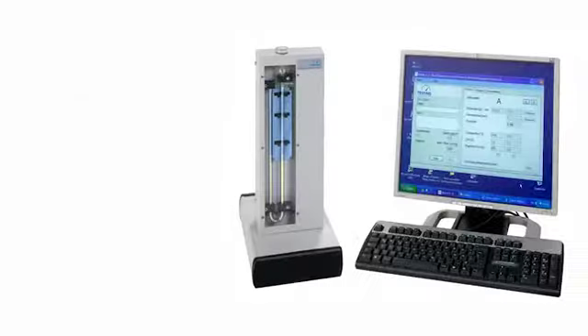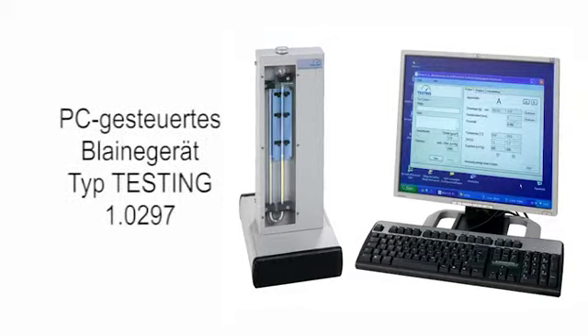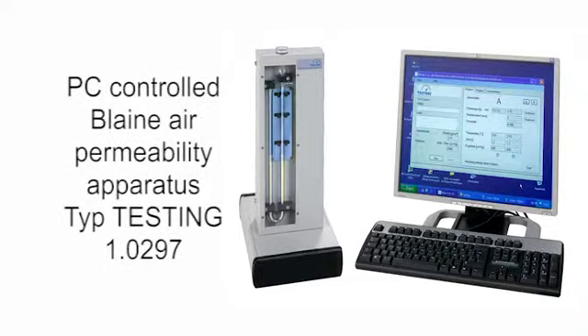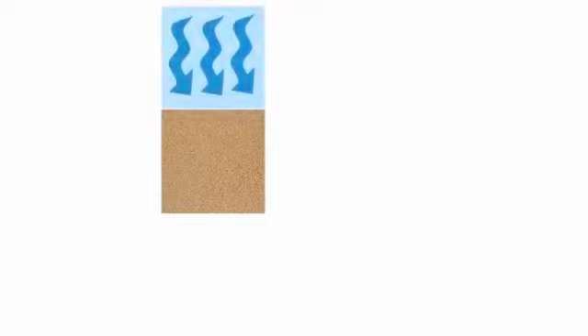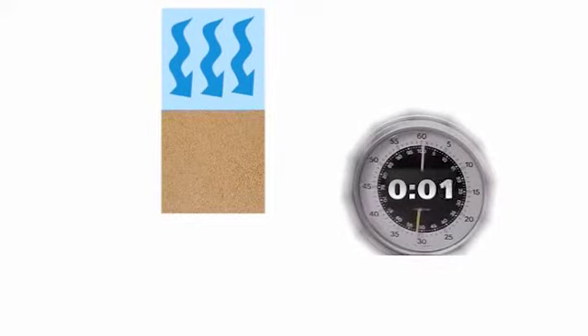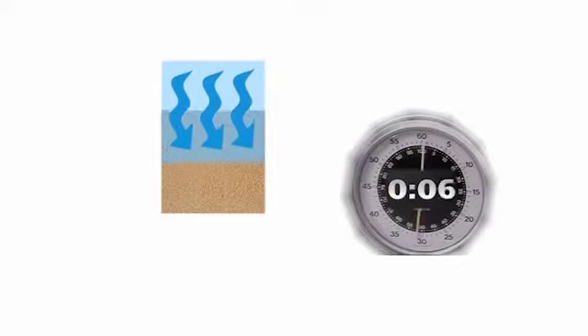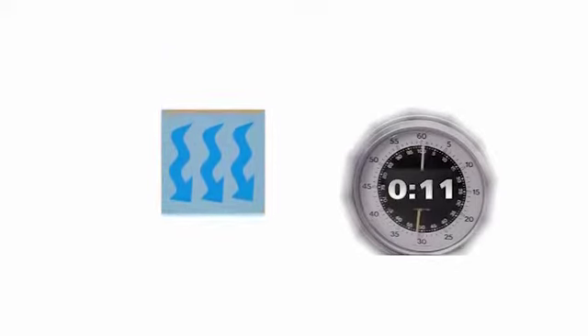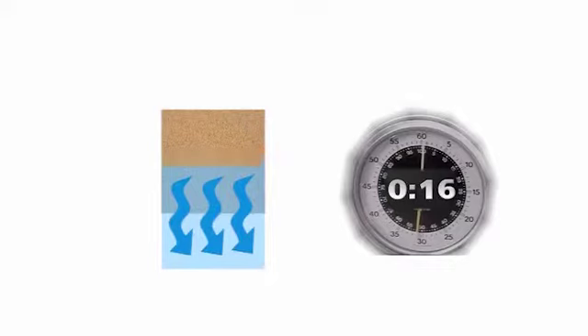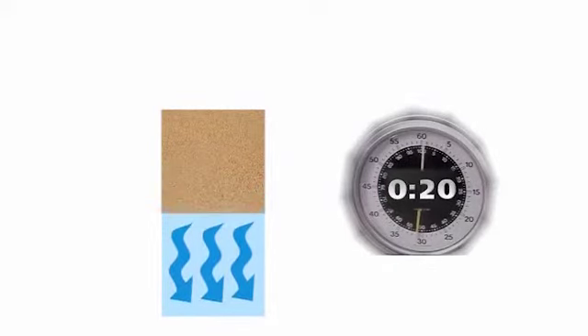The PC-controlled electronic Blaine device number 1.0297 is used exclusively to determine the grinding fineness of cement and should only be used for this purpose. To determine the grinding fineness of cement, its specific surface area must be established from the air permeability of an accurately defined compacted cement bed. This is done by observing the time taken for a fixed quantity of air to flow through the cement bed. This time is then a measure for the specific surface area, which is indicated in square centimetres per gram.